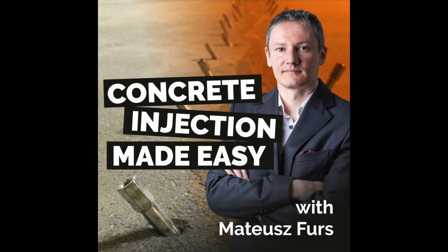Injection packers. For some reason, the technical datasheets of nearly all EP resins mention surface packers only. But we know for sure that if there is a need to use a higher pressure, the surface packer will not stay glued to the concrete surface. So either you will not fill the crack completely with too low pressure, or you will lose your packer. So how to solve this?